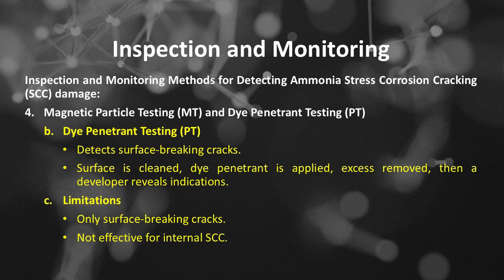Number B, dye penetrant testing, or PT. PT is used to detect surface-breaking cracks. To perform dye penetrant testing, follow these steps: the surface shall be cleaned, dye penetrant is applied, excess removed, then a developer reveals indications. Limitations of dye penetrant testing: only for surface-breaking cracks, not effective for internal SCC.